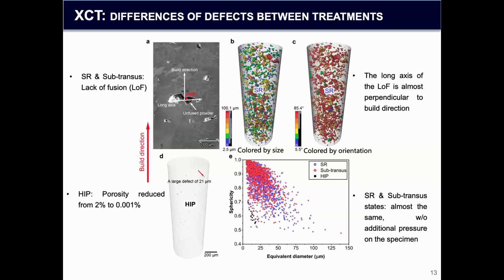And we also use XCT to see the differences of defects between different treatments. So for SR and subtransus, we can still see the lack of fusion defects, and this is the orientation and the size of the defects. And we can see the long axis of the LOF is almost perpendicular to the build direction.